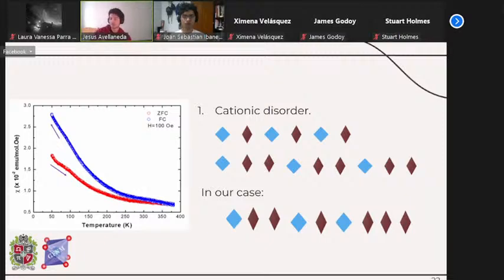Initially, what is inferred from our data is that there are no arrangements of these tiles. As you can see in the top part, there is a certain periodicity between the titanium octahedra and the iron octahedra. Just for clarification, the titanium is blue and the iron are the brown ones. But in our case, we could be having something like the following. In reality, titanium and iron do not follow a specific periodicity, so we cannot determine a global full order of cations in the structure, and this could influence in a considerable way the difference between both curves.